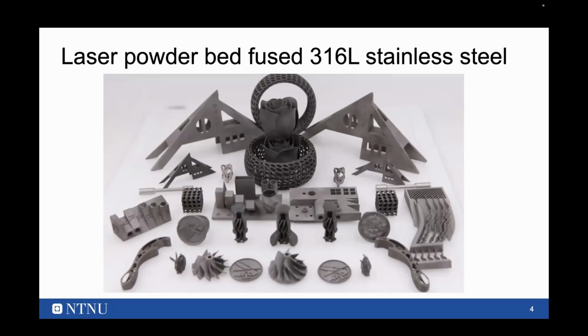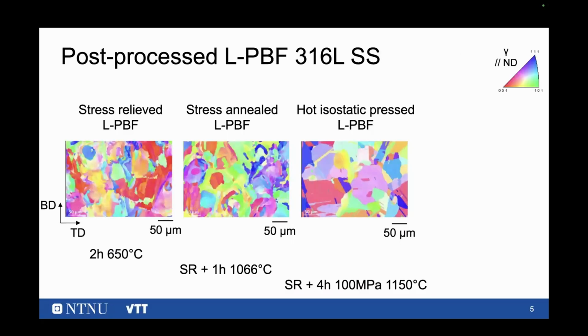resistance to hydrogen compared to the conventionally manufactured 316L, although industry is actually rather interested in post-processed 316L, because it reduces the stacking faults, it reduces all the defects that are formed during the production, and it optimizes the mechanical properties. So here is the evolution.